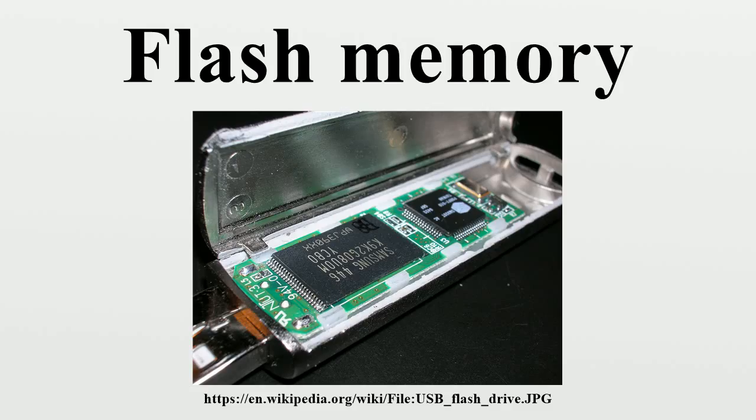X-ray effects. Most flash ICs come in ball grid array packages, and even the ones that do not are often mounted on a PCB next to other BGA packages. After PCB assembly, boards with BGA packages are often X-rayed to see if the balls are making proper connections to the proper pad, or if the BGA needs rework. These X-rays can erase programmed bits in a flash chip. Erased bits are not affected by X-rays. Some manufacturers are now making X-ray-proof SD and USB memory devices.